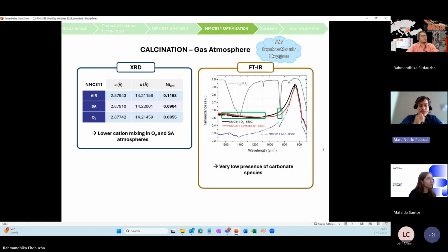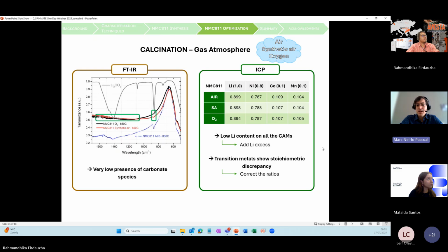Next slide. And to do so, we did some ICP measurements. And what we did see was a bit surprising, not so much for the lithium part, as we were expecting some lithium evaporation. In this case, if you check the lithium of the samples, you see that there's a 10% deficiency on all the samples. It should be around 1, not 0.9.